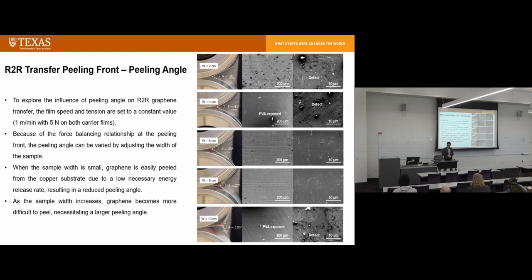Different peeling angle. So we measured the peeling angle: for the 2 centimeter width sample, the peeling angle is 34 degrees. 4 centimeter is 41 degrees. And then for the 6 centimeter sample, we have 65 degrees, and so on and so forth, all the way to 10 centimeters. Of course, the peeling energy required is much higher. Then the peeling angle is 105 degrees. So we use 5 Newton on both top and bottom.